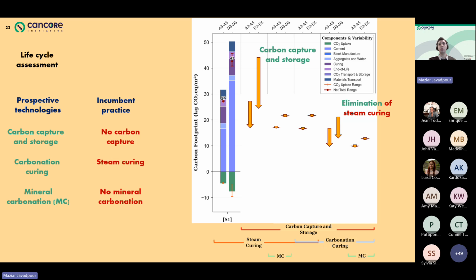So now that we know a little bit about the carbonation curing and natural uptake, let's take a look at the full life cycle results comparing different scenarios. Here we have the prospective technologies: CCS, carbon capture and storage, carbonation curing, and mineral carbonation, and the incumbent practices, which are no carbon capture, steam curing, and no mineral carbonation, of course. Steam curing is what we use right now, especially for concrete blocks, which carbonation curing is really targeting. And this is our incumbent practice for both of the concretes that we saw before, the 15 MPa and the 30 MPa. And of course, as you can see, the 30 MPa has a higher cement content.